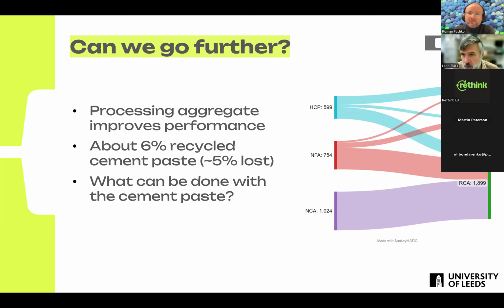We also knew that when we looked at the composition of this, about 80%, so that's the blue material, was cement paste, and about 20% was crushed quartz fines from the sand. So we said, well, what can we do with this? And this is important because if you look at the carbon footprint of concrete, this cement paste actually accounts for about 90% of the carbon footprint.